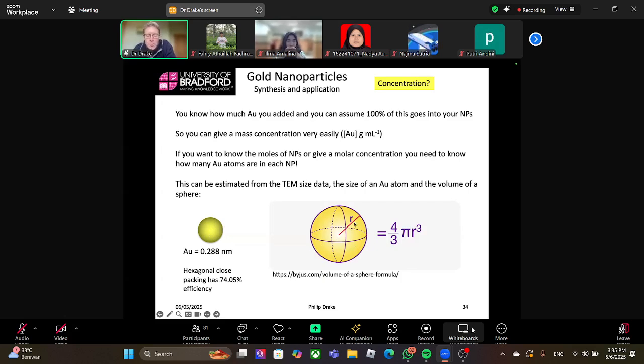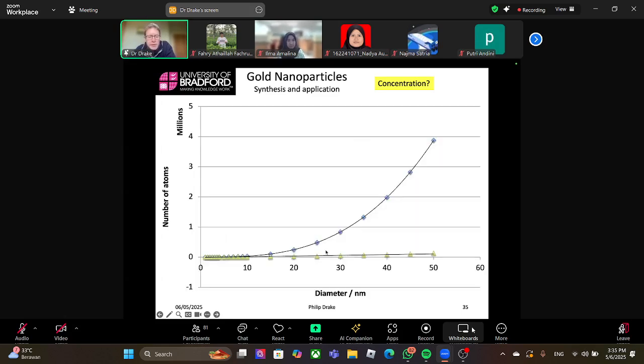Particles form hexagonal close packing. So there's about a 74% efficiency. So there's 26% of the volume has nothing in it. So work out the volume of your big sphere, times it by 0.74, gives you the volume of your gold. Divide that by the volume of one gold atom, gives you how many atoms are in the nanoparticle, the sphere system. And then we can plot them out.